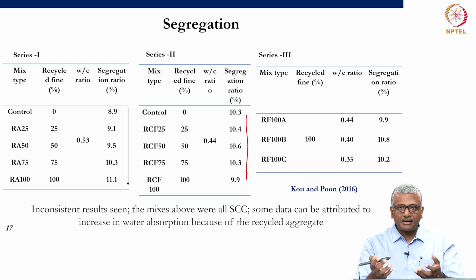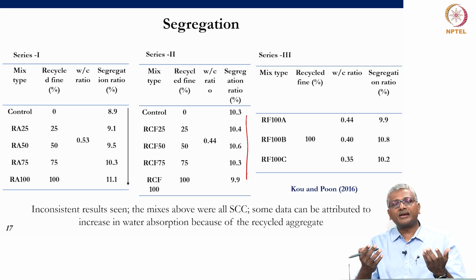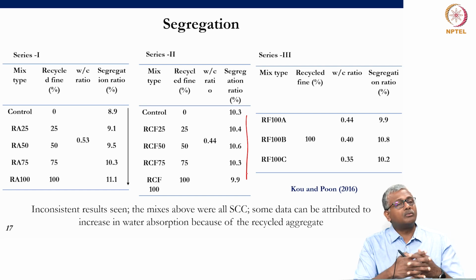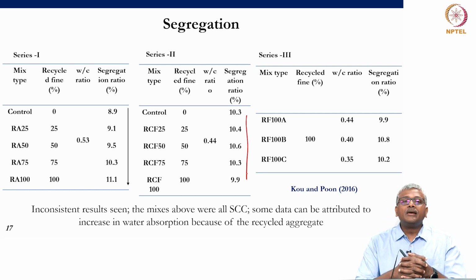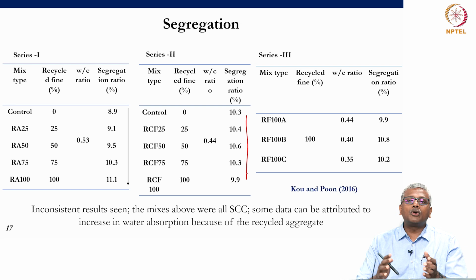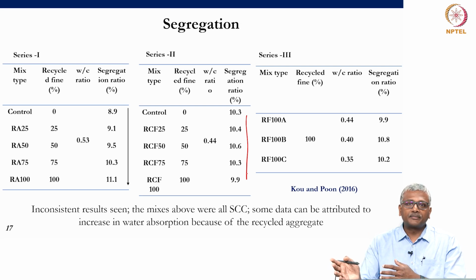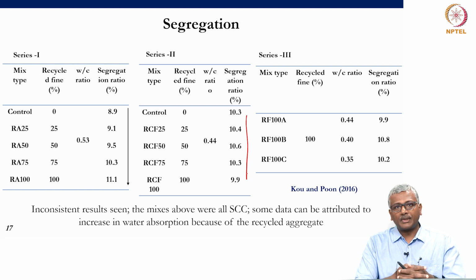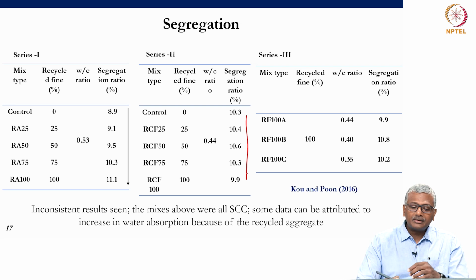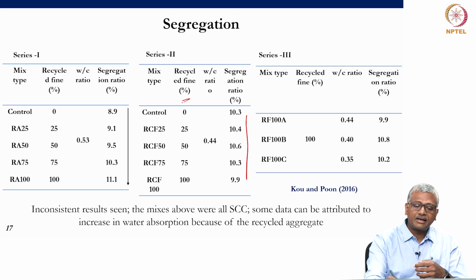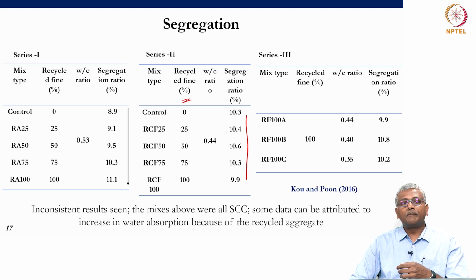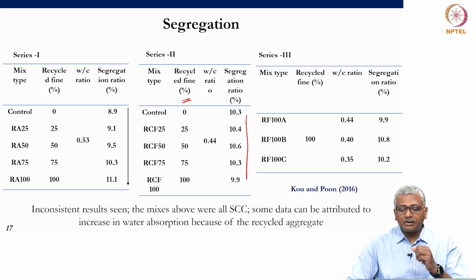So, if there is a lot of segregation, the amount of aggregate that is actually present in the top 1/3, 1/2 of the bucket is not going to be equivalent to the amount of aggregate that is there in the actual mixture, right. So, you can then define what is called a segregation ratio, right. So, here what is seen is segregation ratios depending upon the extent of fine aggregate replacement by recycled fine aggregate did not really vary that much.